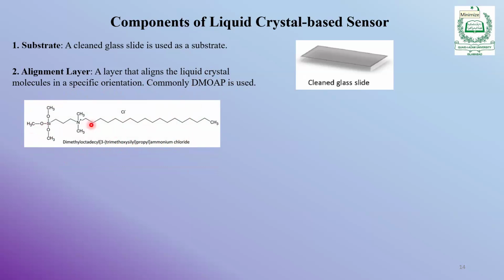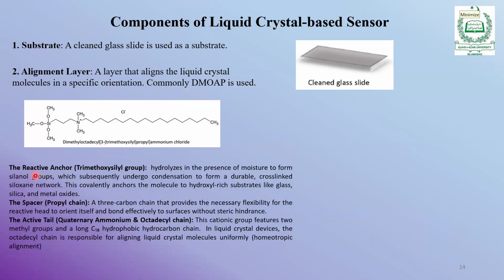So you see, this is a long chain molecule with the silicon oxide moiety here and ammonium moiety here and a long hydrophobic chain. Now this molecule has three parts: the reactive anchoring part, the trimethoxysilane group. These are the hydrolyzable groups. So in the presence of moisture, they can form silanol groups, which can undergo condensation to form durable cross-linked siloxane networks. This covalently anchors the molecules to hydroxyl-rich substrates like glass, silica, and metal oxide. So on glass, if they are hydrolyzed, the glass has OH, so they will be joined here with the glass substrate. Okay? So this is hydrolyzable.